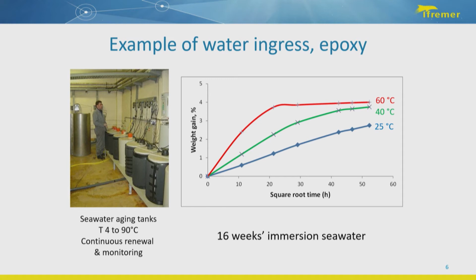So here we have an example where we have three temperatures. At 60 degrees, after about a month, the sample is fully saturated. The water level is stable. At 40 degrees, it's just getting there after about 4 months. And at 25 degrees, it would take probably about a year.